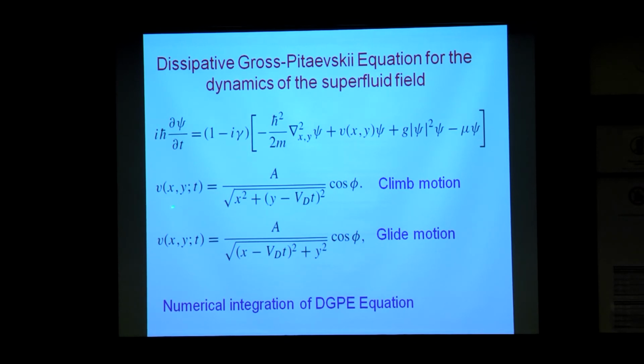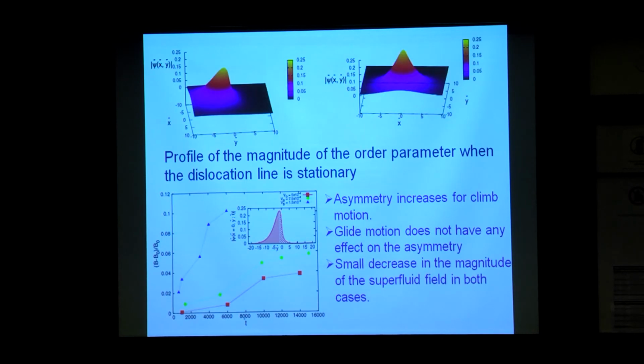The motion of the dislocation line is given by its position. The position is changing either in the y direction or in the x direction, and these two directions correspond to climb and glide motion of the dislocation lines. And what one found is that it doesn't have much of an effect, so it's kind of a negative calculation. This has some effect on the shape, on the distribution of the superfluid order parameter near the core of the dislocation line, but the strength of the order parameter near the dislocation line does not change as we make the velocity go from 0 to some finite velocity. So I'll not go into details about that.